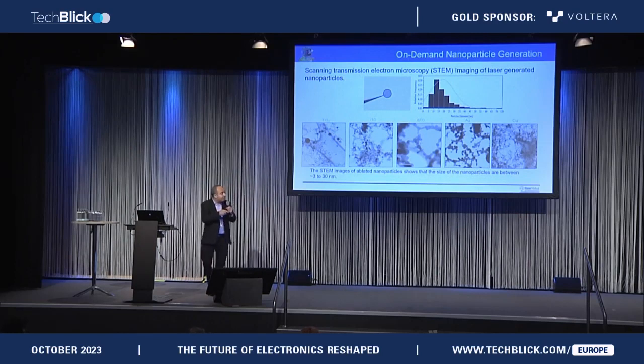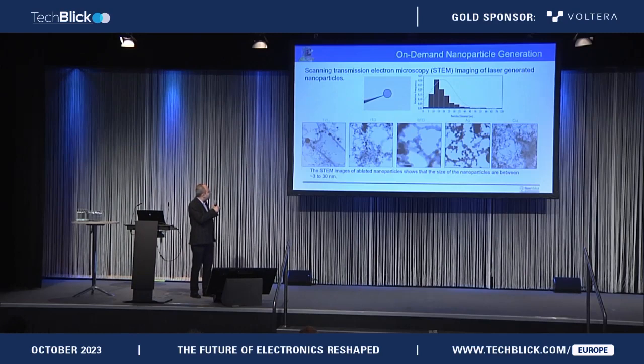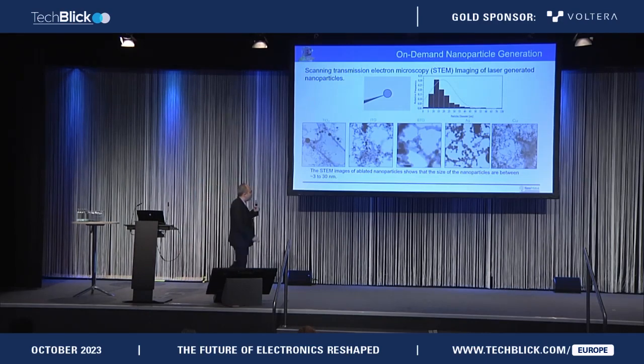These are some examples of the nanoparticles that this machine generates in real time. For example, this one is titanium dioxide, ITO, BTO, silver, copper, and so on and so forth. These nanoparticles range between 3 nanometers to 25 nanometers. The average diameter is about 10, 15 nanometers only. And they are 100% pure.